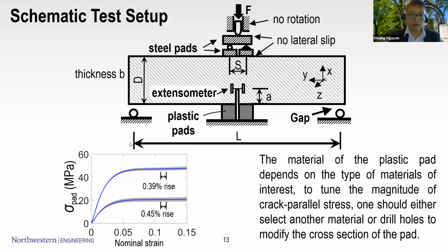So it should be made from a material that can produce such a behavior. For concrete, I found a material called polypropylene that has a very clean and very good yield plateau, where the rise of the plateau is around 0.39% when the moment starts to apply. And you can change the level of crack-parallel stress by changing the material to other materials that have similar behaviors, or you can design the cross section of this material to modify the crack-parallel stress that you want.